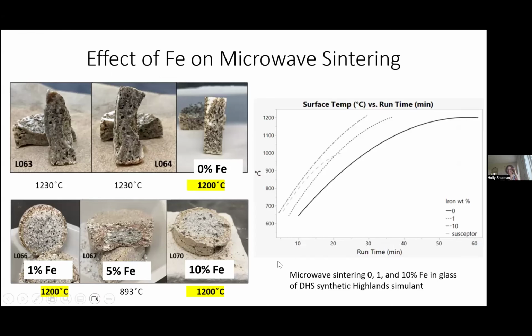Okay, so this is what we came out with. And I want to first focus on the right on this graph. The aim was to hit 1200 C and then turn the microwave off. They're all running at the same power level with the same thermal package. The 0 iron is here, and you can see absolutely it is taking longer to get to that 1200 C. So it's not heating as vigorously as when we had iron. This is the 1% iron, and this is the 10% iron in the glass. And you can see that 10% is really heating very vigorously. And in less than 30 minutes, we're hitting 1200 C.